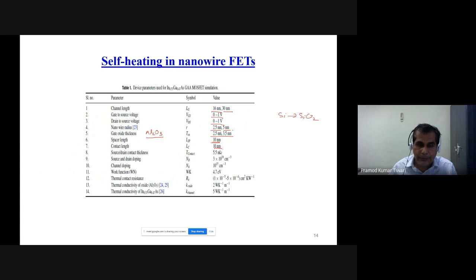Metal contact, that is source and drain contact, thickness was 5.5 nanometer. Source and drain doping was 3 into 10 to the power 19 per centimeter cube. Channel doping was taken as 10 to the power 15 per centimeter cube. Work function 4.7 electron volt. Thermal contact resistance was in this range, 1 into 10 to the power minus 5 to 5 into 10 to the power minus 4 centimeter square Kelvin per watt. The thermal conductivity of the oxide is 2 watt per Kelvin per meter, and the thermal conductivity of indium gallium arsenide is 5 watt per Kelvin per meter.